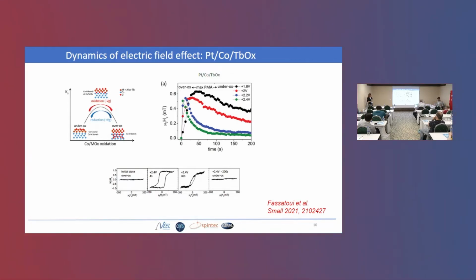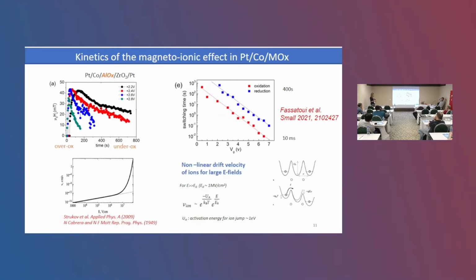And then what you can see is that as you increase the voltage, of course, you accelerate the process so that the switching occurs faster. I don't have the time to show you, but by a very simple model we can model this variation of the anisotropy, this fast variation at the beginning and this slower variation after the maximum, just by assuming a parabolic variation of the anisotropy and a logarithmic variation of the oxidation rate as a function of time. This is in our paper here.